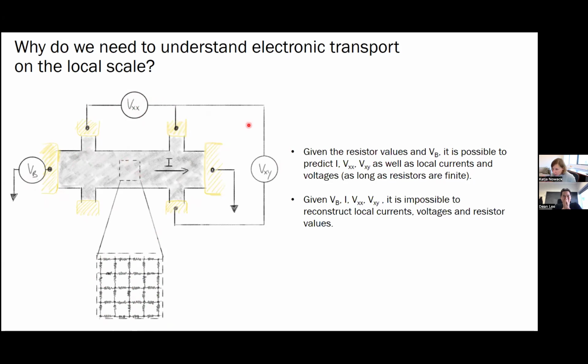However, it's important to point out that the inverse is not true. If we do what we do in the lab and we do this transport measurement, we get four numbers. We know the bias voltage, we know the current, we know Vxy, we know Vxx. But it is in principle impossible to reconstruct all these local resistor values. We can't reconstruct how the current is really flowing inside the device and what the local voltages are doing.